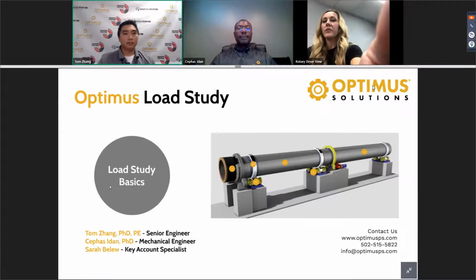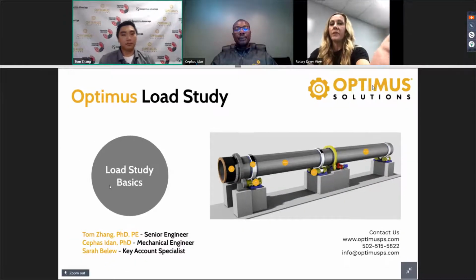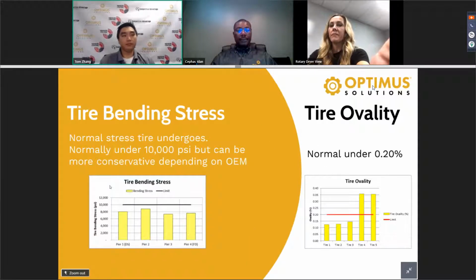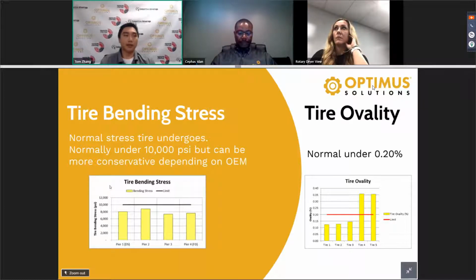So if you have a tire that's extremely worn on one pier, for example, does that increase the chance of it having a higher stress? Yes. We did a study on a unit that had, and this is extreme, a tire thickness of 4 inches, and they had ground every year on the tire. So this is where we put the clause in that we normally don't recommend grinding all the time. So there may be some melt. So they ground that from 4 inches to 3 inches.